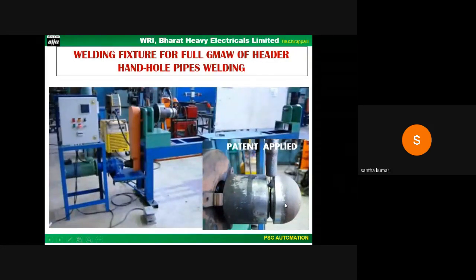Dished ends were another challenge, as the weld should meet 100% RT quality as per ASME and be subjected to proof testing by hydrostatic test at the shop. A mechanized welding fixture has been developed to make the root pass by STT, the waveform control process, because here we have gone fully GMAW. Earlier it was done by TIG welding for the root pass and further passes by manual GTAW or GMAW or SAW or SMAW. But by developing this fixture and by automating, we brought waveform control processes into this, and a fully GMAW process has been developed. This has replaced the manual GTAW and SMAW processes and increased the quality and productivity level. We could achieve a 600% increase in productivity by this mechanization.